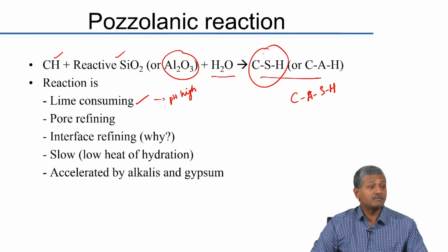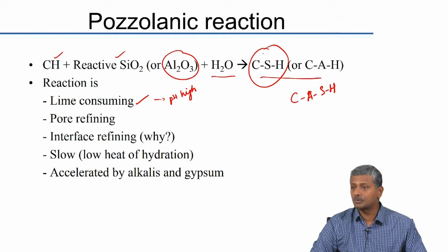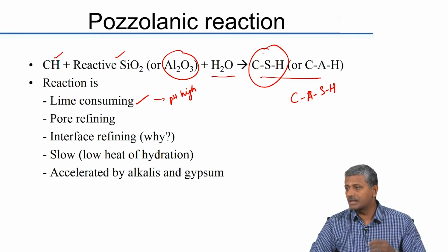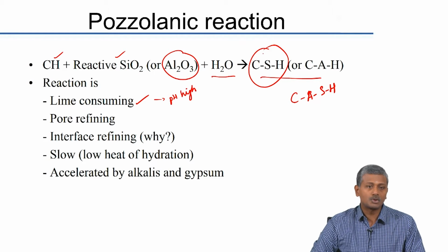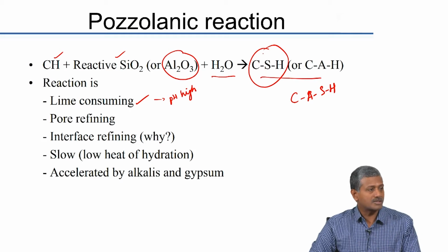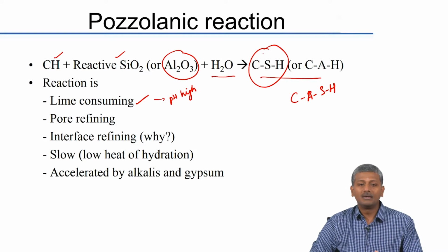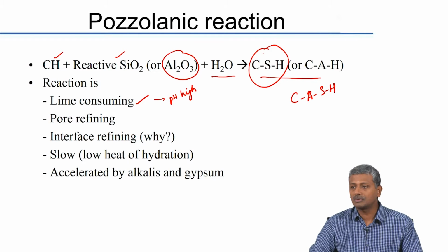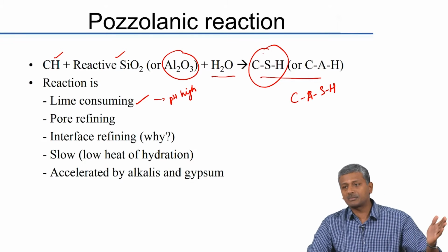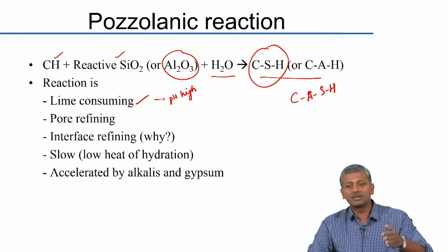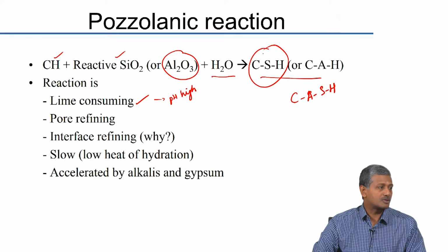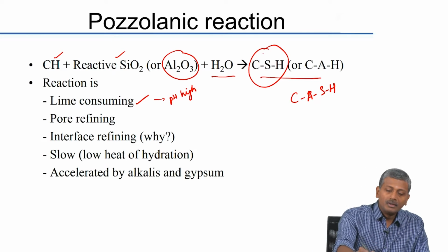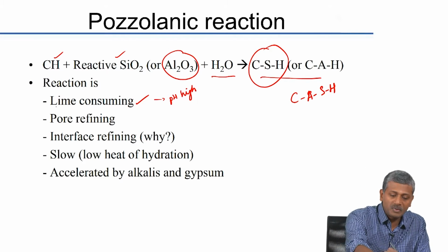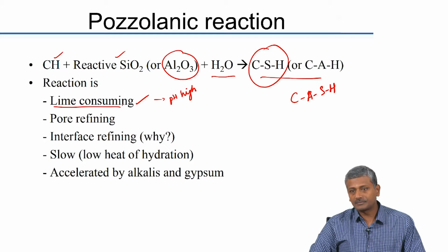For example, even when soft water passes through concrete, it can actually leach out your calcium hydroxide. Soft water, which is a neutral pH, can actually leach out your calcium hydroxide, which is often why you see white patches on the surfaces of your brick walls or even sometimes concrete. The white patches are basically calcium hydroxide that has leached out and converted to calcium carbonate on atmospheric exposure, okay. So, lime consumption happens, which makes the system a little bit more durable, okay.